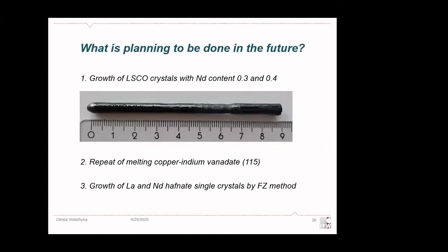And what is planned to be done in the future? There's the growth of LSCO crystals with neodymium content 0.3 and 0.4, and I showed you what is already done. This was the first trial for the LSCO growth with neodymium content 0.3. The growth finished last Friday, so it's freshly obtained, and as you can see, we obtained quite sufficiently long part of the single crystal grains in this crystal.